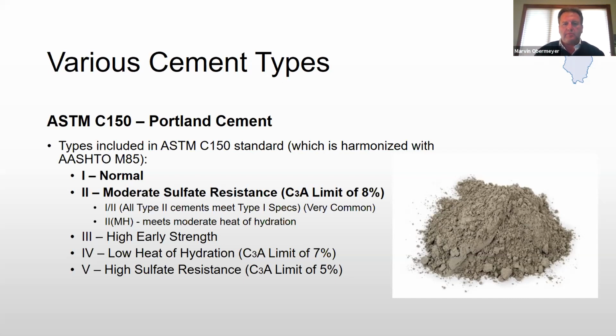One of the notes: type 2 moderate sulfate resistance has a tricalcium aluminate limit of 8%. Okay, so the C3A is limited to 8% on type 2 cement, whereas on type 4 cement, the C3A is limited to 7%, and that's low heat of hydration cement. Usually, if you see a type 4 cement, those were used back in the day when they built Hoover Dam and all the big structures that were built in the 30s. That's very rare now. It's very, very difficult to find a type 4 cement.